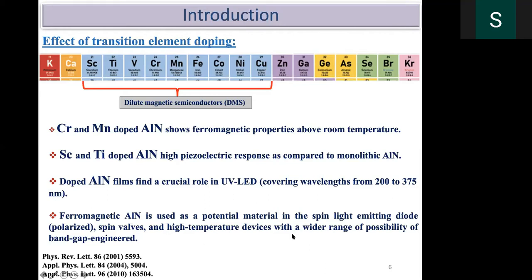I said why it is a high temperature material, because aluminum nitride is a very highly insulating material, but interestingly, also highly heat conducting because of the phonons. Even though it is called a wide band gap material, with 6.2 eV band gap, when you dope with some elements, it will come to the semiconducting side. But this particular compound is a very good heat conducting material.